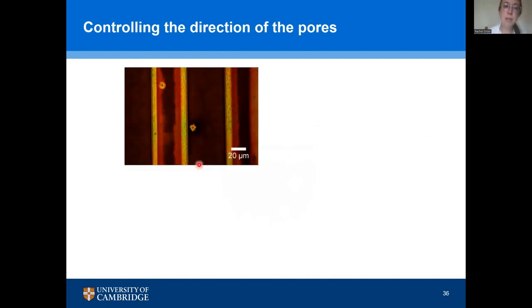So when we put a sample like that into the polarized light microscope, well, to start with, this is just a standard light microscopy image. And you can see that we've not etched all the way through our material. So we've got our trenches here. On the edge, we've got successful etching. We've got a little bit of etching that goes up to about 20 microns in, and then we've got an unetched region at the center. And that kind of illustrates the limitation of this kind of radial approach. We've also got one place here where there was a hole in the silicon nitride where it's etched from the top, which is why there's a bright spot there.